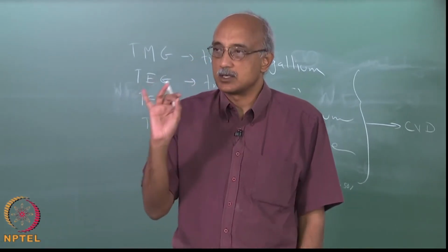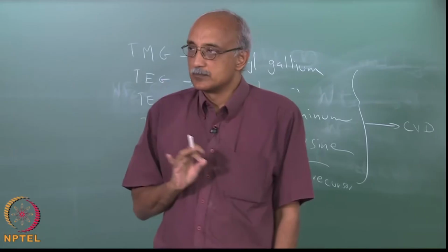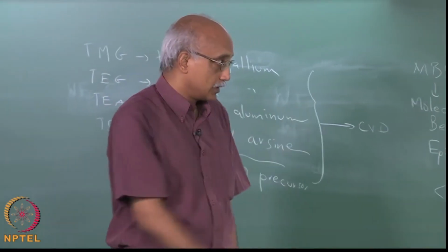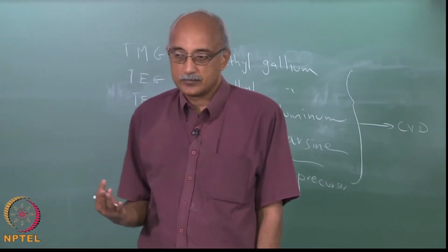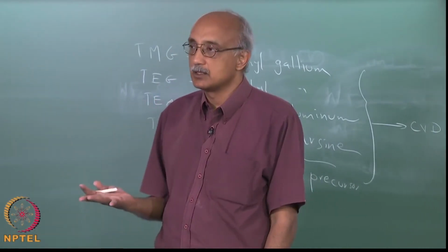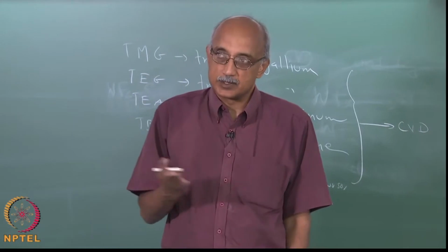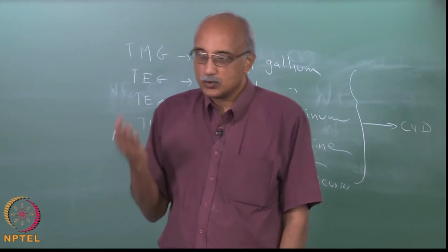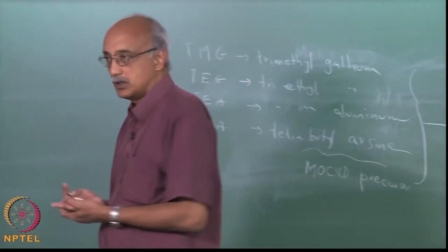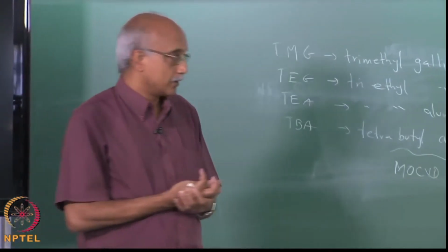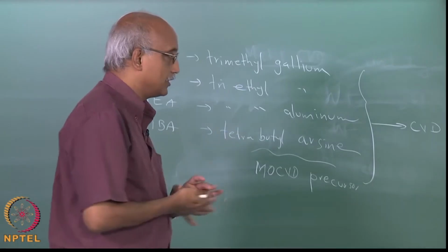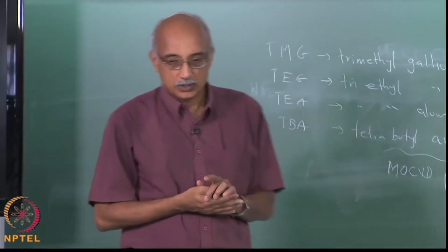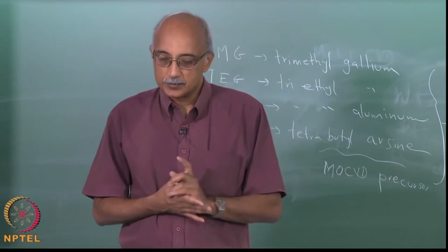Essentially you are picking spots on the metal and heating them, whereas in the case of MOCVD you are pretty much reacting the entire bulk material to make the metal vapors. And so you get a much more uniform feed when you are doing metal organic CVD type of processes. So, this MOCVD process is now widely used also to make metal films.